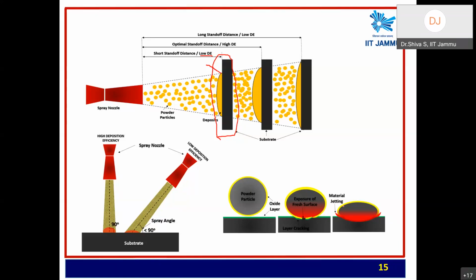And the next level is the substrate. What happens here is that as this impingement is being done with a low efficiency, as the distance keeps on increasing, the powders will start slowly drifting away from the absorbed energy, because the kinetic velocity from the expansion lasts in that excited state only for a certain limit. After that, the absorbed energy will start drifting away from the deposition track. So as an effect of that, the impingement will not take place as efficiently as you would like, and the deposition efficiency gradually falls. So this is the reason, between three different layers, that it is important how the standoff distance has to be efficiently chosen for high deposition efficiency.